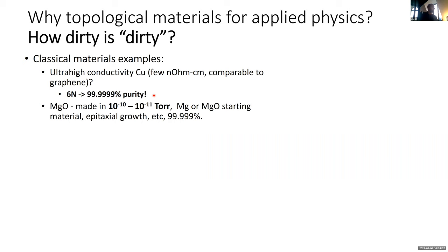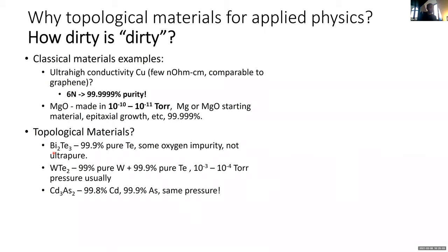So just by contrast, in topological materials, the bismuth telluride crystals we grew were not that special. The tungsten ditelluride, we started with 99%, so 2.9s pure tungsten, and not very pure tellurium, in much higher pressure. Cadmium arsenide, not even 3.9s of cadmium, which is known to have other kinds of metals dissolved in it. So it really is not very clean. And yet you saw those mobilities, those properties.